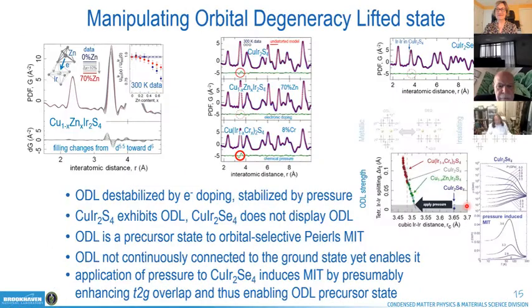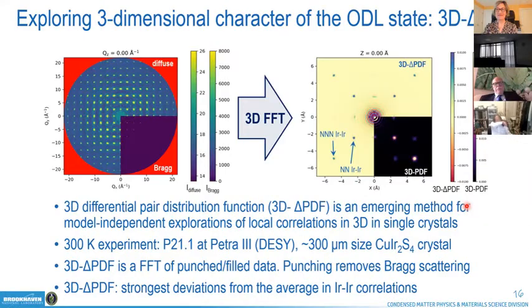Okay, so this has been a set of measurements on powder, so it's always good to test if the same type of phenomenon takes place in single crystals. And for that matter, we also wanted to address the 3D spatial character of this ODL state. And so for that purpose, we have performed so-called 3D differential PDF type of measurements, where basically you collect a full map of scattering in reciprocal space, then you separate diffuse and Bragg, which is essentially critical for this. Bragg is your signature of the average structure, and diffuse is obviously measuring the deviations from it. And then you 3D Fourier transform it, and what you end up with is essentially a 3D map of interatomic vectors in space, which you can then interrogate in a model-independent way.